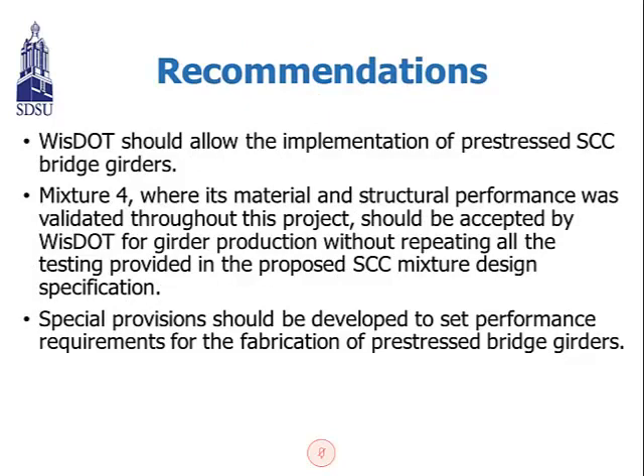So according to the discussion and all the results and conclusions with the technical panel, we made the recommendations as follows. Wisconsin DOT should allow the implementation of the prestressed SCC bridge girders. And the mixture 4 that we used for this project should be accepted by Wisconsin DOT for girder production without repeating all the testing provided in the proposed SCC mixture design specification, because we already tested and demonstrated the effectiveness of mixture 4 in terms of workability, compressive strength, creep and shrinkage, prestress losses, etc. And a special provision should be developed to set performance requirements for the fabrication of prestressed bridge girders.